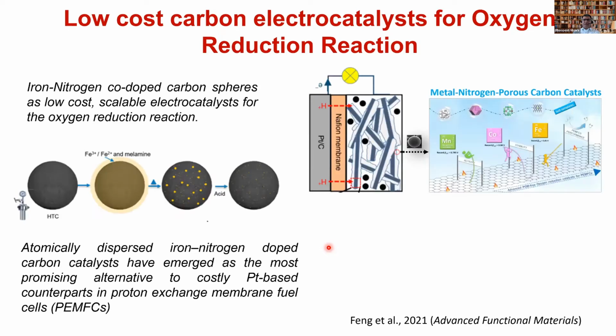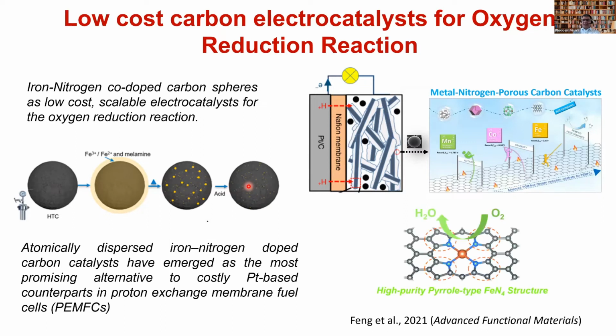So what they did is that they started with HTC. They started with sugars, and then they doped nitrogen during the formation of HTC. Then they put iron into that system as iron chloride, and then they pyrolyzed that, and they formed beautiful FeN, FeC kind of products, and then they etched that with an acid bath, and what they had ultimately is a beautiful FeN4 kind of material, which we helped them showcase. And this high purity FeN4 structure is very good for the oxygen reduction reaction. And this is just a schematic showing that this kind of technique has multiple applications. Also, although this was not the first time it was shown, this was a demonstration that FeN4 can do very good ORR reaction.